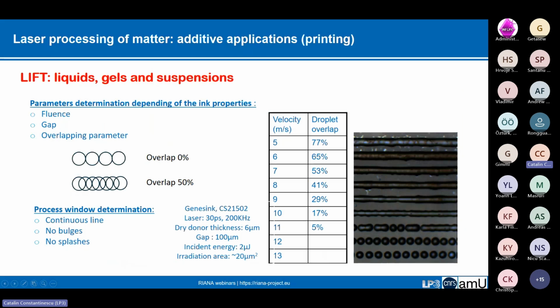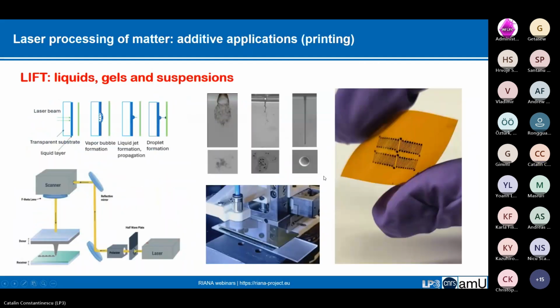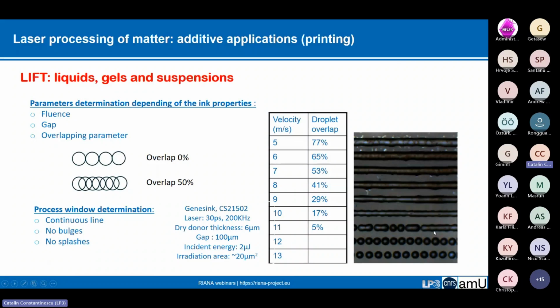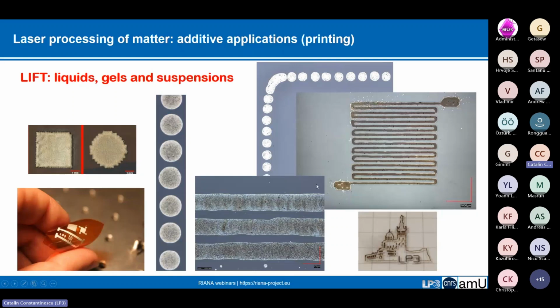So we need to understand how this process takes place, how tuning the fluence, how tuning the gap between the donor and the receiver, and the overlap of the droplets need to be taken into consideration with respect to the rheology of the material used. So therefore, we identified the regimes that produce continuous lines without the splashing, which is crucial for functional printing. So this enables real device fabrication. So by controlling the droplet overlap and understanding how lines are formed, we can print continuous lines, structures, and so on and so forth.